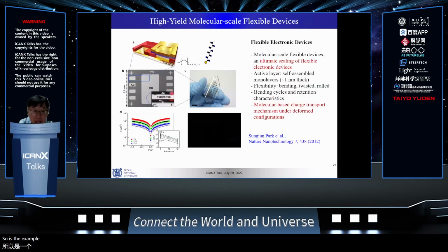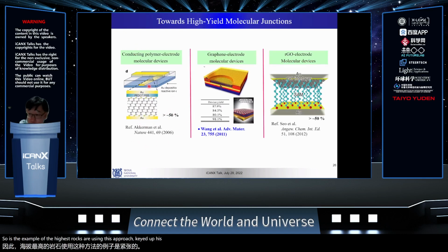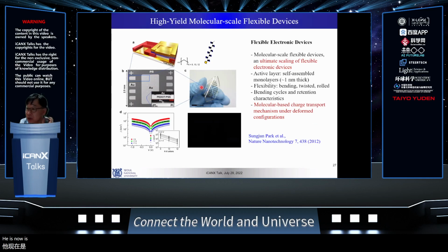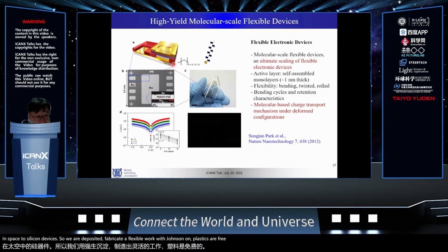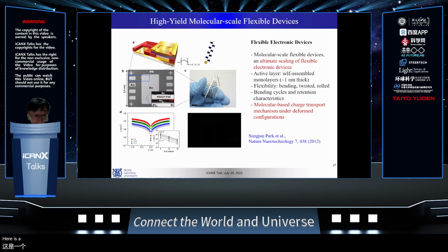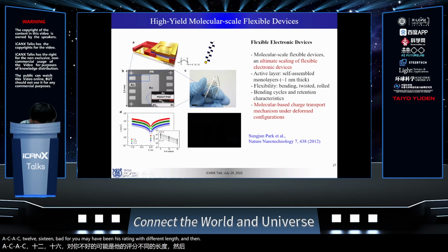So this is an example of the high-yield structure using this approach, with PEDOT:PSS conducting polymer. Now, if this is really a high-yield platform, then you can make it flexible. The advantage of organic electronics is flexibility, in comparison to silicon devices. So we fabricated a flexible molecular junction on a plastic substrate. Here is the plastic substrate, bottom gold, and molecular monolayer, with an interlayer of PEDOT:PSS right there. The molecules are insulating molecules with different lengths: C8, C12, C16, that I told you about many times.